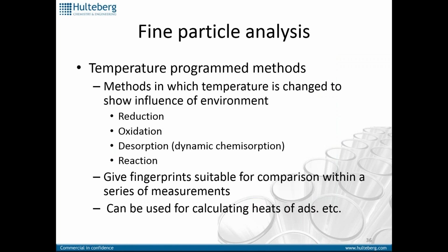Chemisorption can also be done in a temperature program mode, and in this case we call it dynamic chemisorption. We can do, for instance, temperature programmed reduction, oxidation, desorption, or reaction, and this will give us nice fingerprints for comparing within a series of measurements.